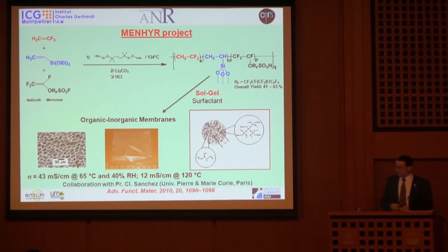Okay, I understand that you can say, okay, we put silica inside, and in acidic conditions, obviously, the membrane will not be very efficient. We didn't try that. We didn't try in fuel cell test and even the degradation. But what was very interesting on this membrane is that the conductivity was 43 millisiemens per centimeter at 65 Celsius, and we could reach 12 millisiemens per centimeter at 120 with 100% relative humidity, which is quite interesting for this work. So again, the design of a depolymerization which was non-controlled.